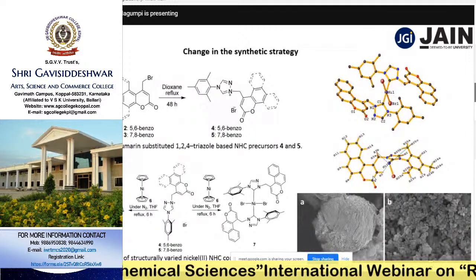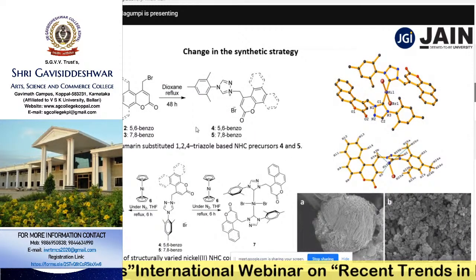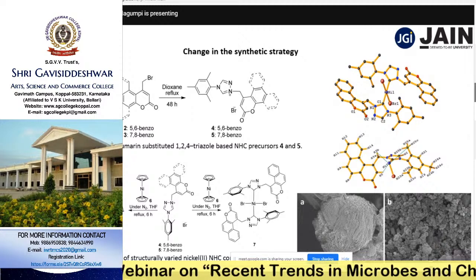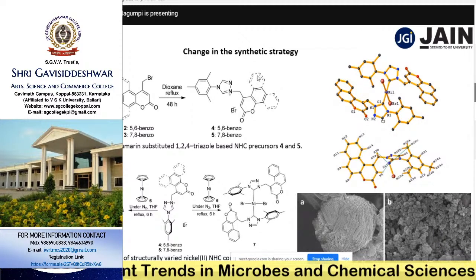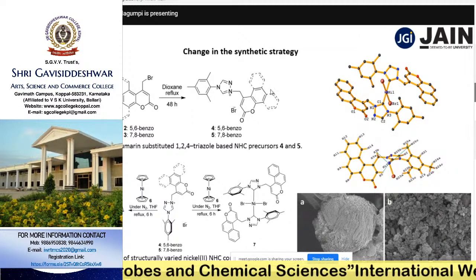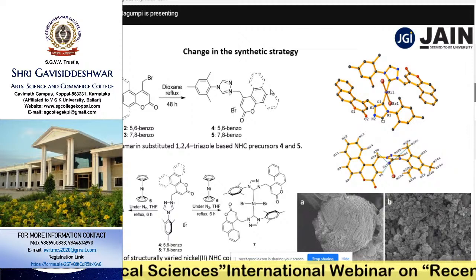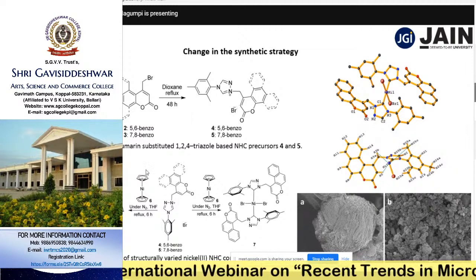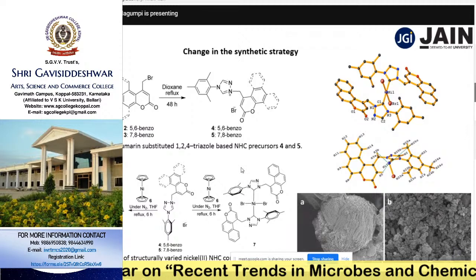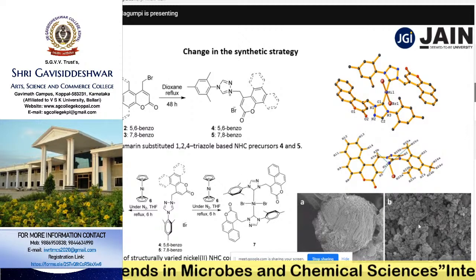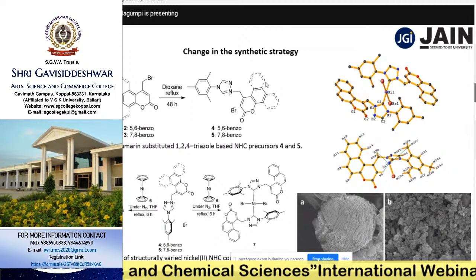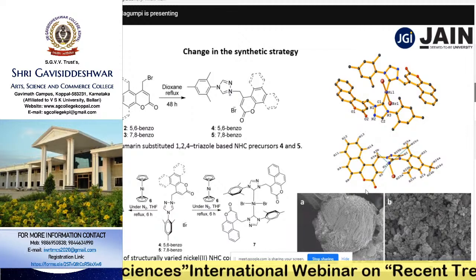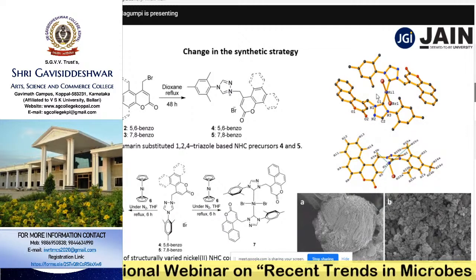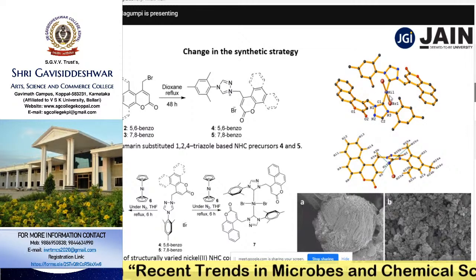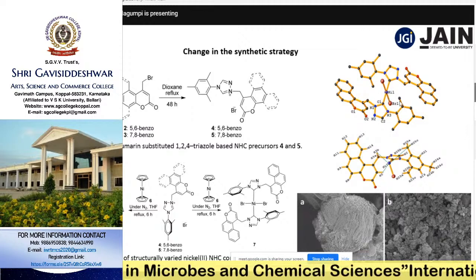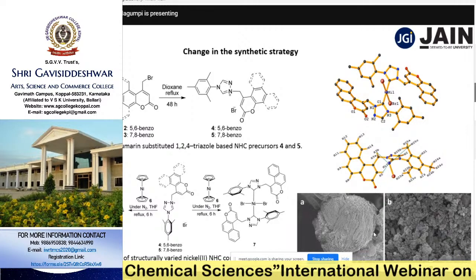Similarly, we have changed the synthetic strategy here. We have changed the synthetic strategy in order to get a few more substituents to get more sensitive or more effective glucose materials. So these two particular complexes were also prepared in order to tune the morphology. These substitutions are varied in order to tune the morphology as well as the sensing ability. So here we have ended up with the 4-coordinated nickel complex, which is established by the single crystal X-ray diffraction technique, and these are the morphological studies.